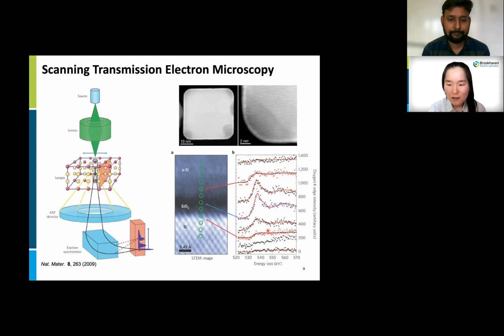And the oxygen K-edge spectra here were acquired at the green circled areas. We can clearly see that the oxygen K-edge is definitely different in silicon oxide. And think about it, the silicon oxide is only 5 angstrom thick, so it is a very powerful technique. And with high angle annular dark field detectors, we can get chemical information from images too.